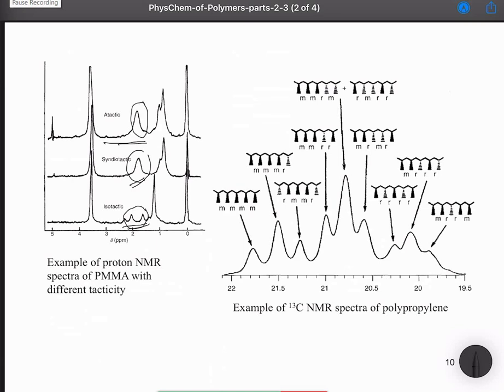The spectrum of atactic (heterotactic) polymethyl methacrylate shows a dominant singlet peak, similar to a syndiotactic structure. This tells us that the atactic structure of PMMA contains a higher percentage of syndiotactic asymmetric centers than isotactic ones. This NMR method is a very convincing way to identify and analyze polymer tacticity for R&D purposes or any analytical task.